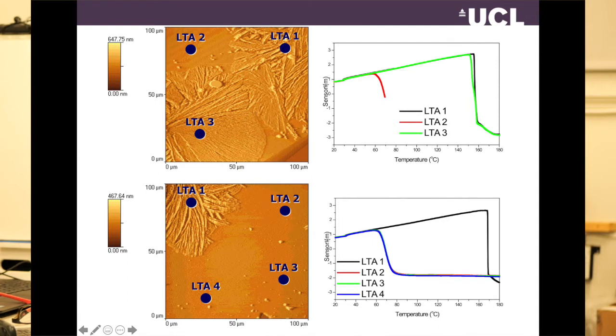Clever, huh? So here are some examples of indomethacin tablets again. So you look at the two images on the left-hand side. They're two separate images of the same compact. Now, I've said many times, crystalline material tends to look as though it's got sharp edges, and amorphous material tends to look rather smooth. So I think in this case, it's indomethacin in a polymer. The indomethacin is crystalline and the polymer is amorphous. So if you look at the top image, most of that image looks as though it's crystalline. So it looks like there's a lot of drug at the surface of the compact, but there's one region in the top left-hand corner where it looks quite smooth. So it looks like that might be polymer.